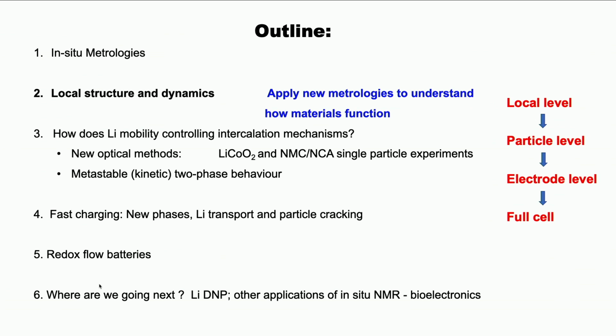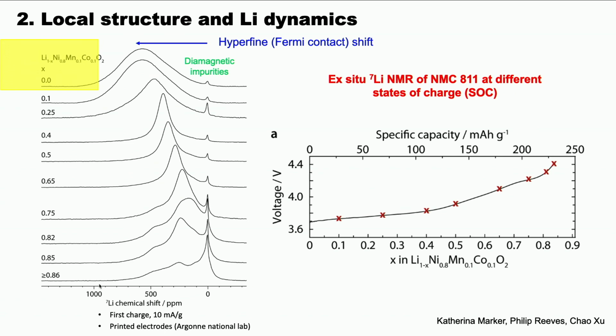I want to now lead you through a story where we're going to connect local structure all the way through to mechanisms for how materials intercalate. And so the story starts with this material NMC811. So this is the cathode material that's in most of today's electric vehicles. It's a layered compound like lithium cobalt oxide, but you've replaced 80% of the cobalt by nickel and 10% by manganese, so that's the 811.